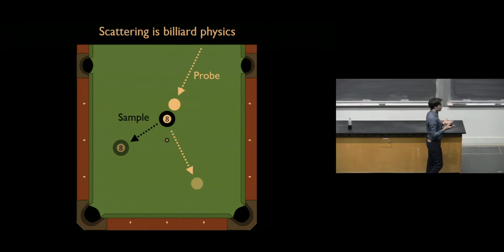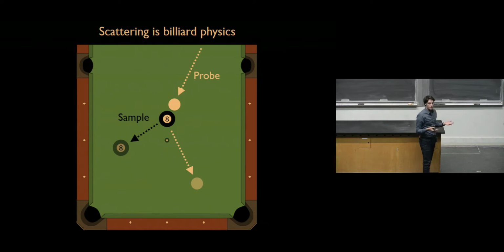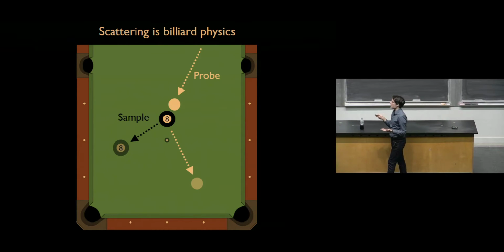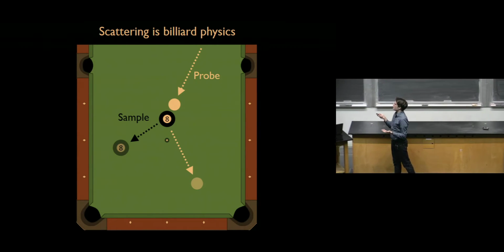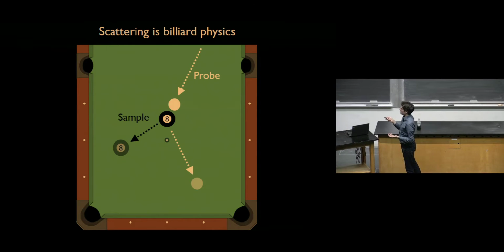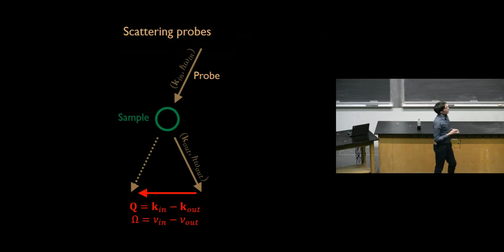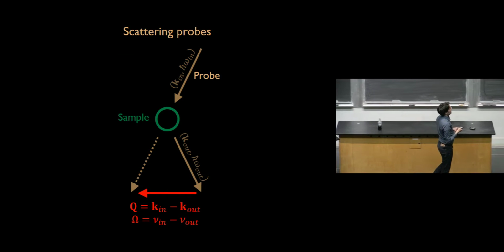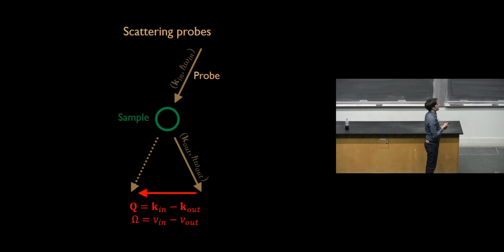The same as in billiards, momentum is conserved in the process. So in the beginning, momentum is only in the probe. At the end of the process, momentum is acquired by the sample and is also taken up by the scattered particle that is going in some other direction. Momentum conservation is enforced in this equation here, which tells us that the momentum that we've given to the sample is equal to the momentum of the incoming probe minus the momentum of the outgoing probe.